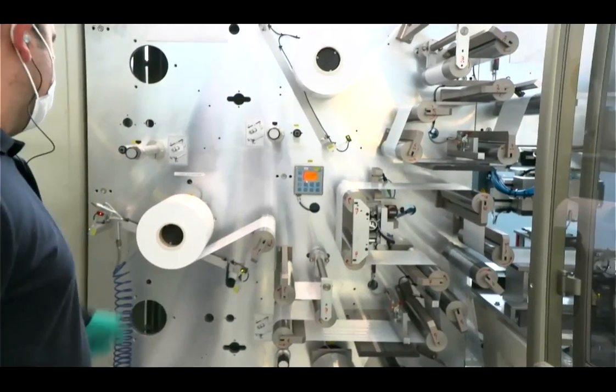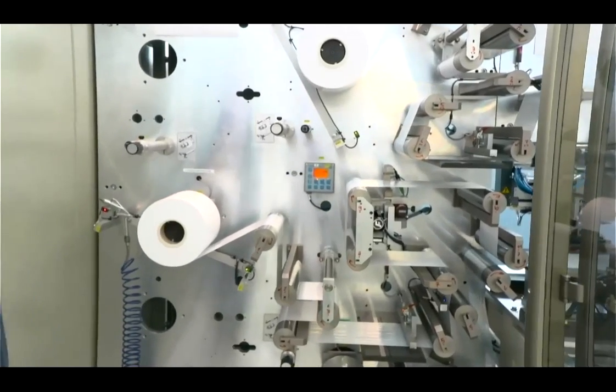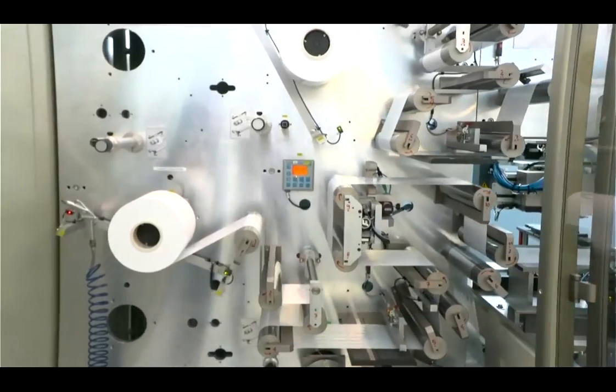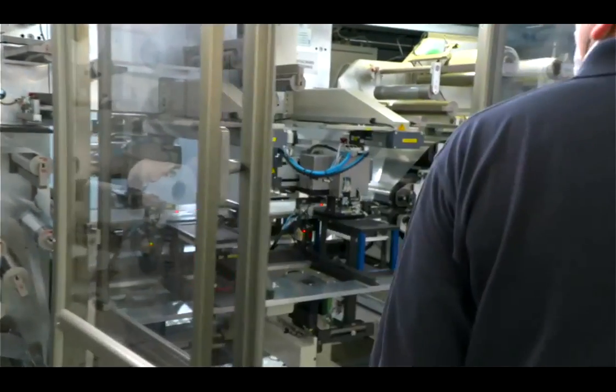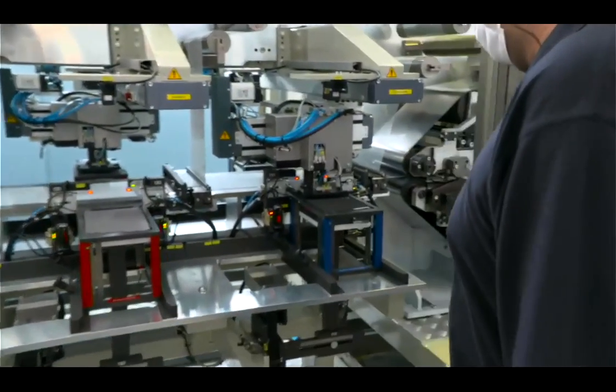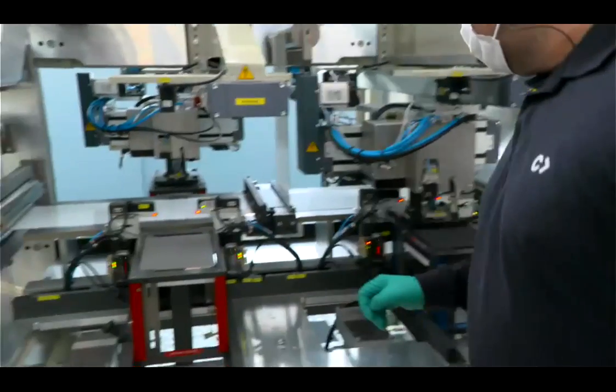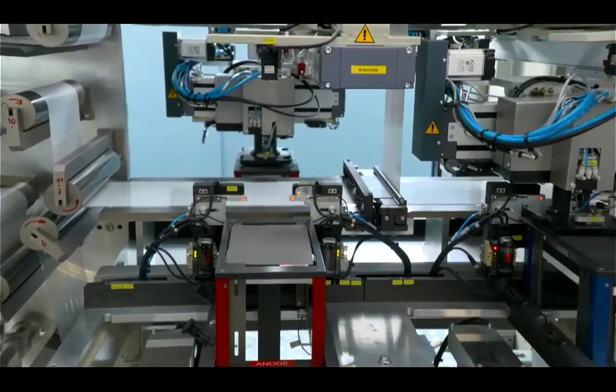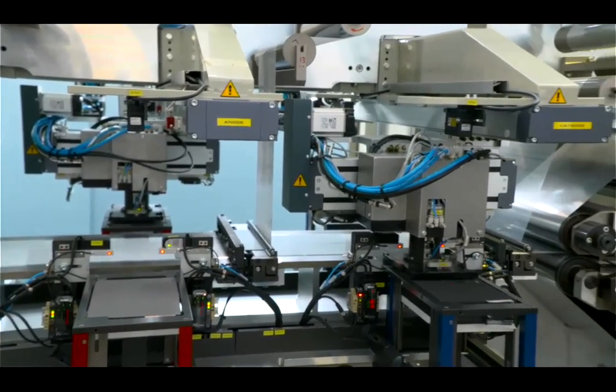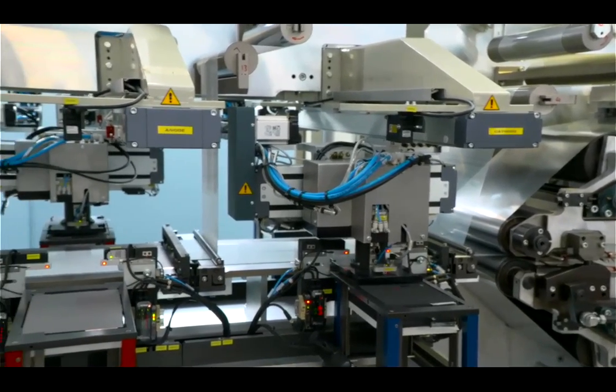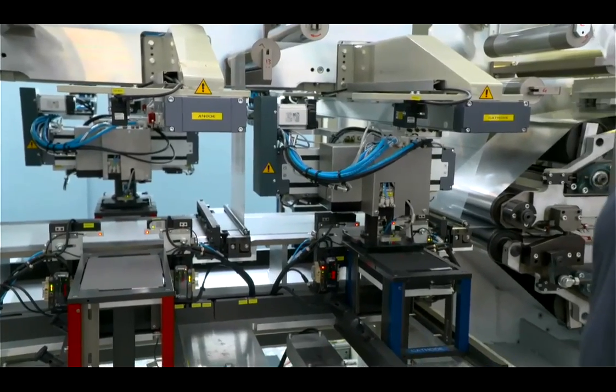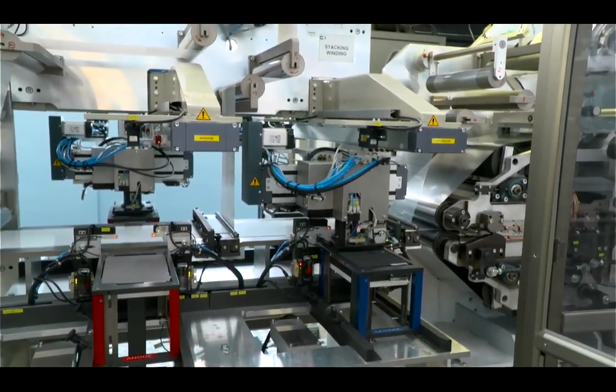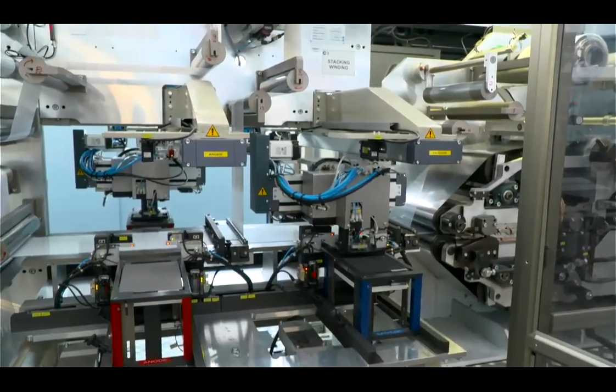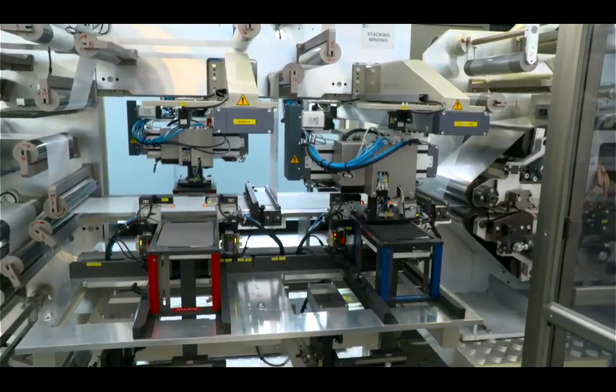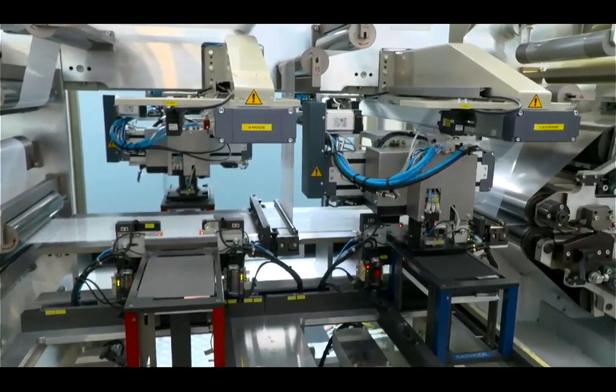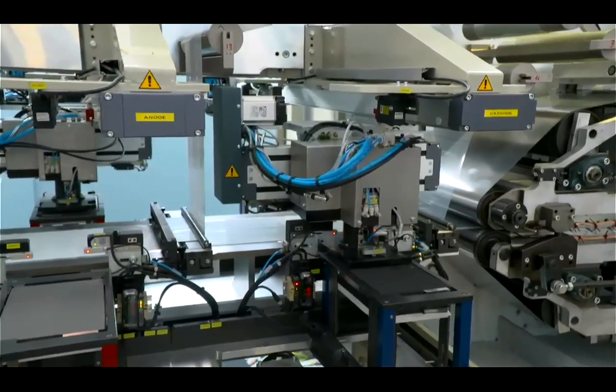Iker is showing the roll of separator. Actually, the appearance of this roll of separator is exactly the same as the appearance of a normal separator. You can find these two different separators in the market, the standard one or, in this case, the laminable one. What is important when you choose the laminable separator is that the PVDF layer has to be very, very thin, because this PVDF layer has to allow the lamination of the electrodes, but it's important not to introduce an additional resistance to the cell, because we are introducing one more layer. It's a polymeric layer, but we cannot allow ourselves to increase the resistance of the cell. So in short, you can find this separator in the market, but you have to choose the good one.